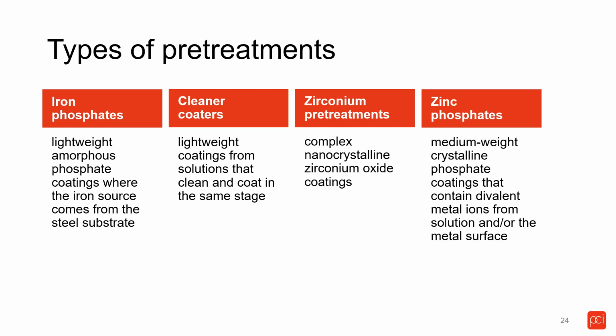Another thing I want to point out with iron phosphates is that there actually isn't iron in an iron phosphate product—that comes from the steel itself. So you can't apply an iron phosphate coating to a galvanized part or an aluminum part. What you end up doing is just etching the surface so you can get a little bit more surface area for your paint to stick.